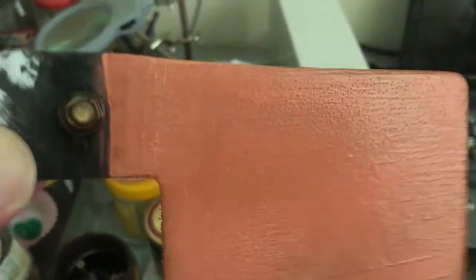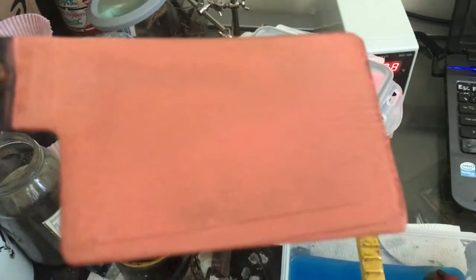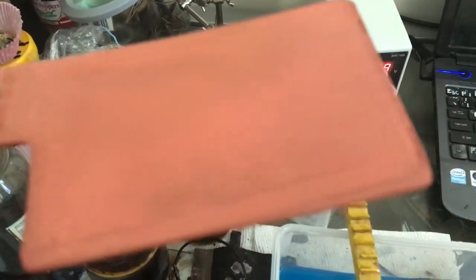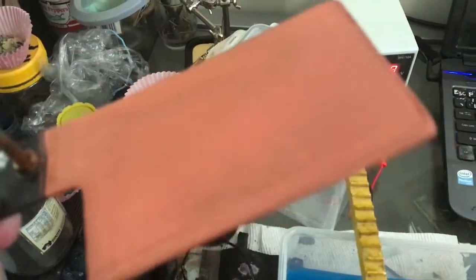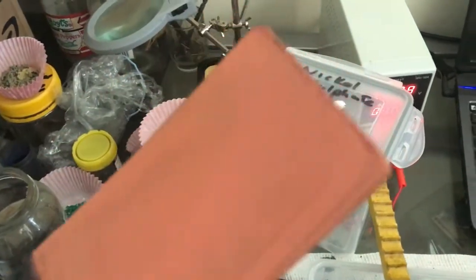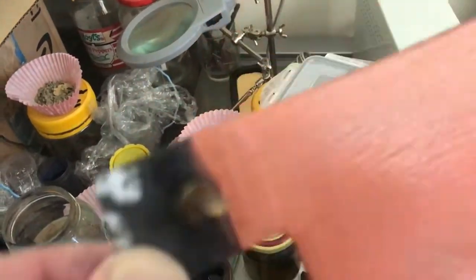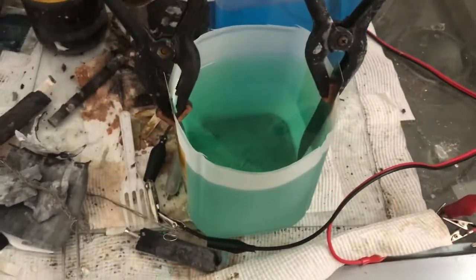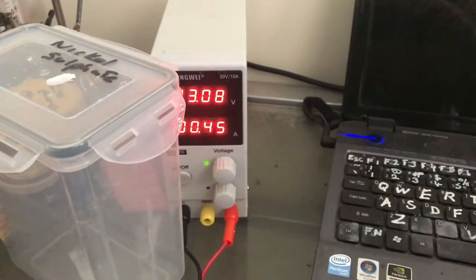There's no peeling with the copper. I've given it a wash underwater a couple of times actually and scrubbed it with a brush. So it should be good. It's completely sealed. Okay, fingers crossed this nickel sulphate works. A layer of nickel just instantly appeared over it. It's running 3 volts at 450 milliamps.